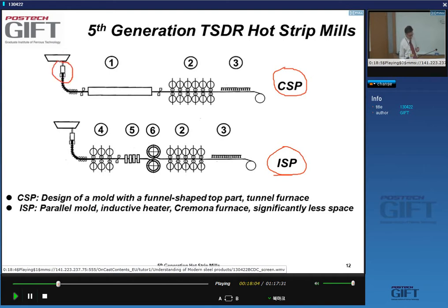The design of the mold here is important. You have a funnel-shaped mold because you need to cast a very thin strip. The mold, instead of being parallel, has this special funnel shape so that you can cast thinner slabs, yes? And it has a tunnel furnace, of course.